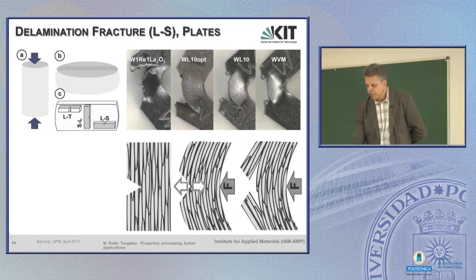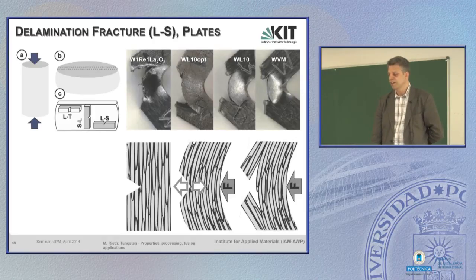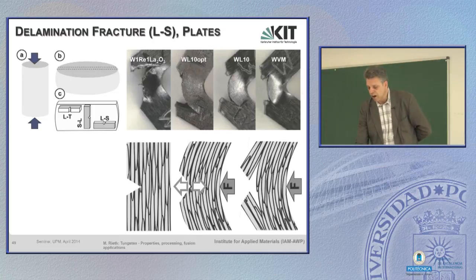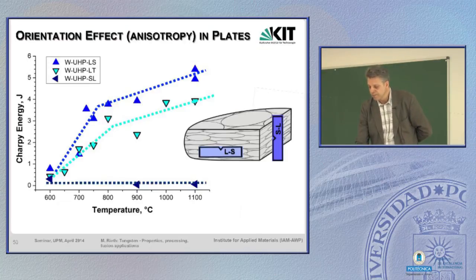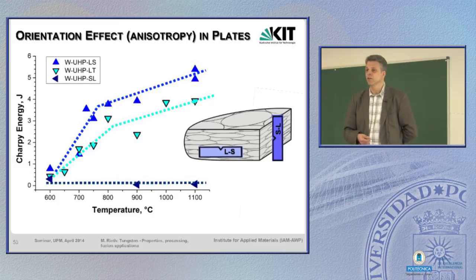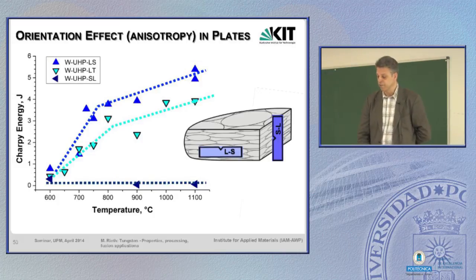And now we have done Charpy tests to see this more clearly. In this orientation, we expect the best possible behavior, and in this orientation, this should show easy crack evolution through the pancakes. And indeed, if you do the tests, the best results are this curve with very high energies. And in this orientation, you can see the Charpy energy measured is around 0. That's nothing. So that's easy fracture, and that's why we have to avoid this type of loading.